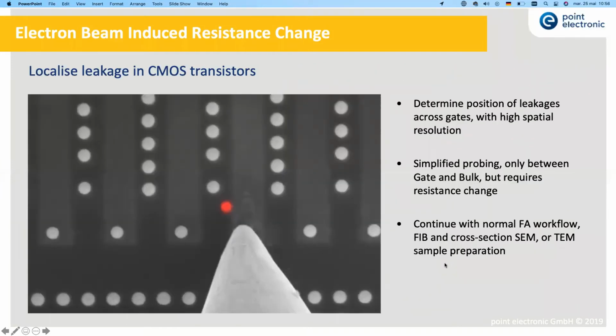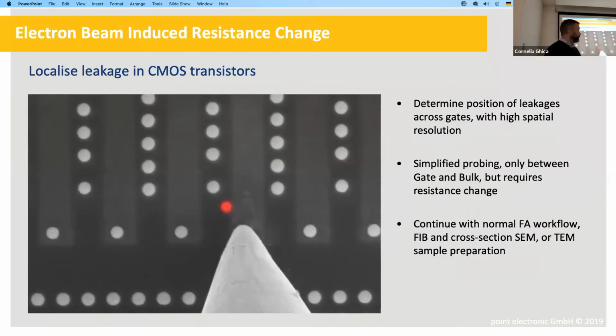And it's a technique used primarily for failure analysis at the moment. I think they are the first ones to really get into it and use it. And what it gives them is the ability to localize defects very precisely. So for example, we're looking at a transistor structure, and this transistor has been measured to have a high leakage. And the question is, why does it have a high leakage? What is the defect? Is it in material, is it in fabrication, is it in the oxide or in the semiconductor? And we are forcing the current through this probe, and we're just watching how that current changes because of the electron beam scanning.